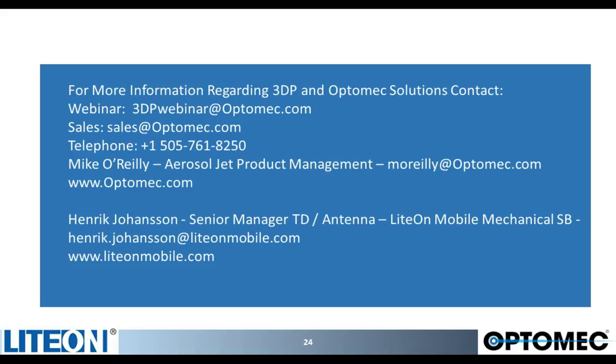Yeah, to some extent at least. We found during development that when we have a plastic part or a substrate which has holes and voids, when ink adds up into the holes, it actually pulls down the wet ink into the holes, which means that the remaining ink on the top surface is too thin to get the needed conductivity. So it means that a molded structure needs to have a smooth and uniform surface we are printing on.